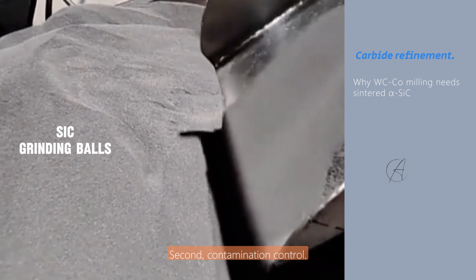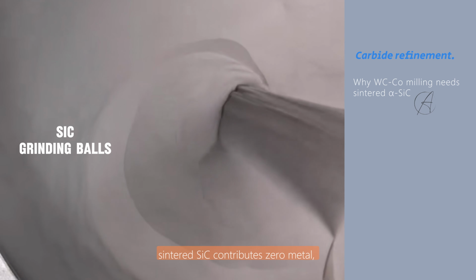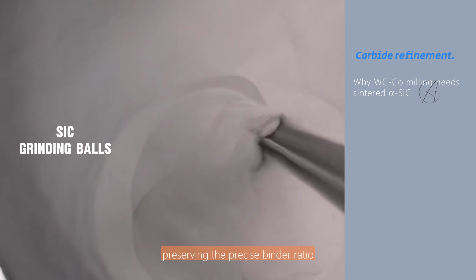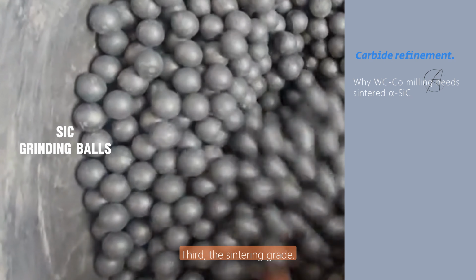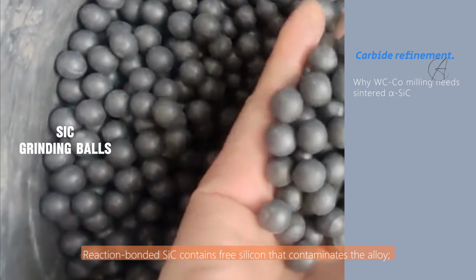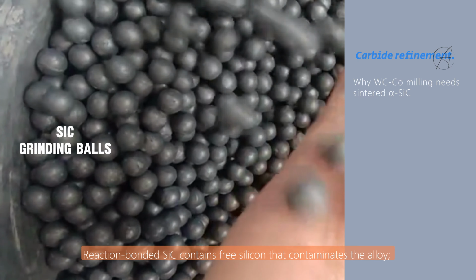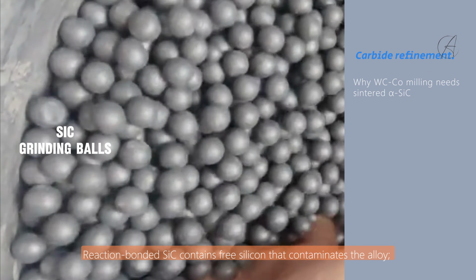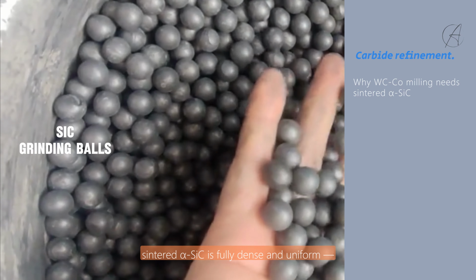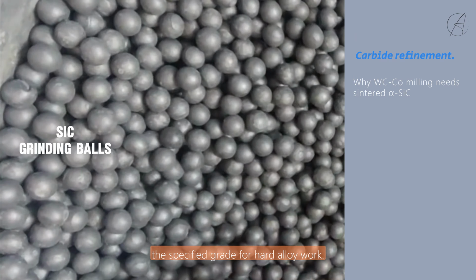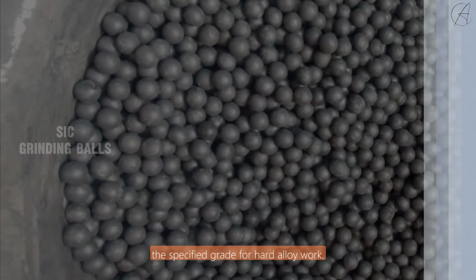Second, contamination control. Hard alloy specifications routinely forbid more than 0.05% foreign oxides in the final tungsten carbide and cobalt composition. Sintered silicon carbide contributes zero metal, preserving the precise binder ratio that defines the tool grade. Third, the sintering grade. Reaction-bonded silicon carbide contains free silicon that contaminates the alloy. Sintered alpha silicon carbide is fully dense and uniform, the specified grade for hard alloy work.